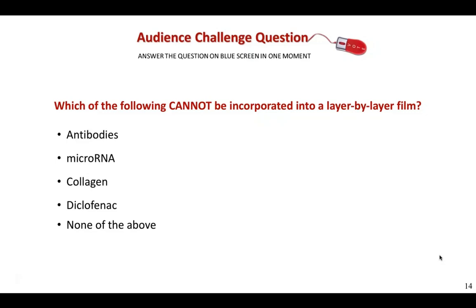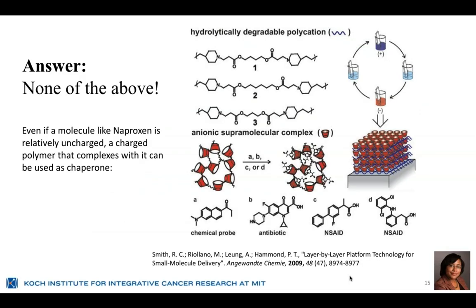Excellent. Thank you, Mike. And it turns out that the audience was correct. None of the above. All of those species that were listed can be incorporated. And layer by layer, we can incorporate large macromolecular charged species. We can incorporate small molecule charged species and natural biomolecules like collagen. But we can also incorporate drugs like diclofenac and other hydrophobic drugs by using a carrier. We can get help from something like a polycyclodextrin, such as the one that's shown here. You can see that these cyclodextrins, which have hydrophobic pockets, can sequester hydrophobic drugs. And there are a number of sulfated polycyclodextrins that are water soluble and can be layered into these films to allow incorporation of even these hydrophobic species.